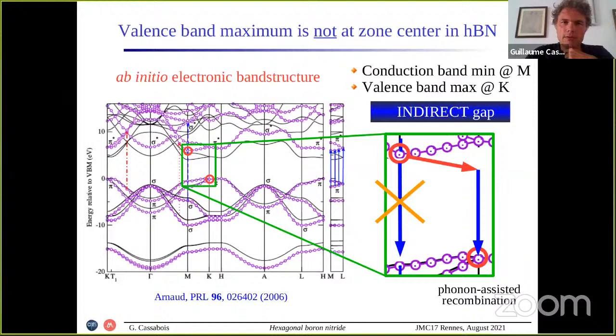Again, I would like to start with very basic physics, condensed matter physics, and start not with the phonon band structure, but the electronic band structure as calculated in this paper, where we have the valence band, which has a maximum around the K point, and the conduction band, which has a minimum around the M point. So the gap is quite huge, as I told you before, 6 eV. If we zoom in, we see a typical configuration of an indirect gap.